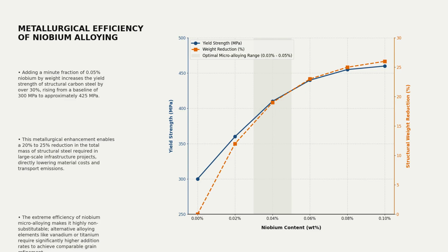Niobium has extraordinary metallurgical leverage. Adding just 0.05% niobium by weight increases steel yield strength by over 30%. This microalloying process allows engineers to reduce structural steel mass by up to 25% in major infrastructure projects. Because alternative elements like vanadium require much higher concentrations, niobium is practically non-substitutable. This chemical efficiency locks global infrastructure and automotive manufacturing into a highly concentrated supply chain.